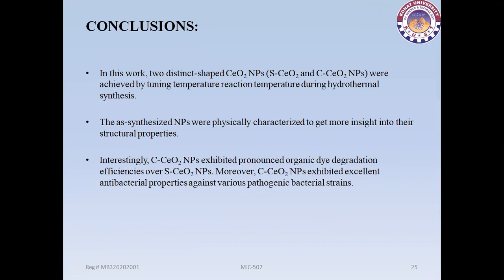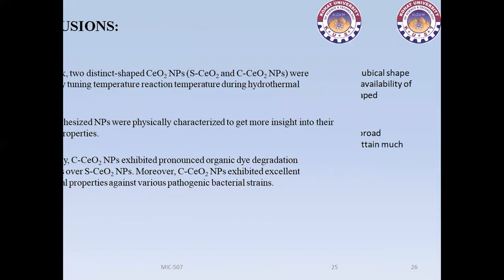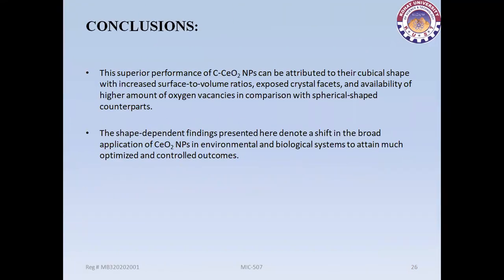Interestingly, the cubical cerium oxide nanoparticles exhibited pronounced organic dye degradation efficiency over spherical cerium oxide nanoparticles. Moreover, cubical cerium oxide nanoparticles exhibited excellent antibacterial properties against various pathogenic bacterial strains, and the superior performance of cubical cerium oxide nanoparticles can be attributed to their cubical shape with increased surface to volume ratio, exposed crystal facets, and availability of a higher amount of oxygen vacancies in comparison with their spherical counterpart. The shape-dependent findings presented here denote a shift in the broad application of cerium oxide nanoparticles in environmental and biological systems to attain more optimized and controlled outcomes.